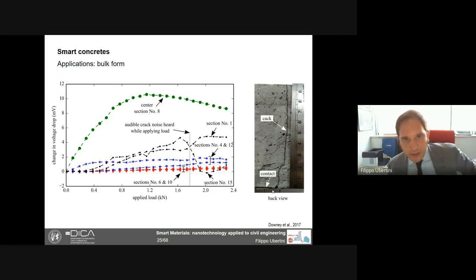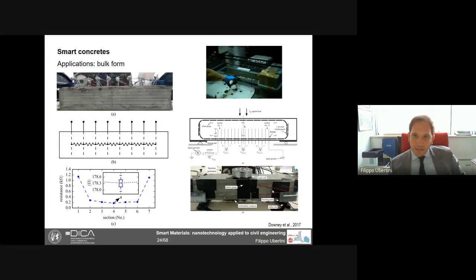So here instead you see the results of the application to the beam. So I go back to the previous slide. You see on the right there is a beam with reinforcement, only longitudinal reinforcement, no shear reinforcement, and this beam is fully made of cement paste with nanotubes. Then we have electrodes all through the beam, and the beam is simply supported, and we do something that is in between a 4-point bending and a 3-point bending. Let's say it's a 3-point bending test.